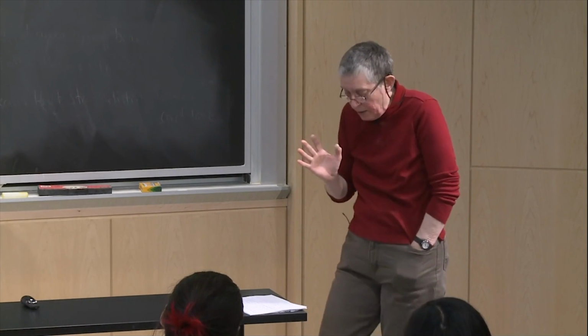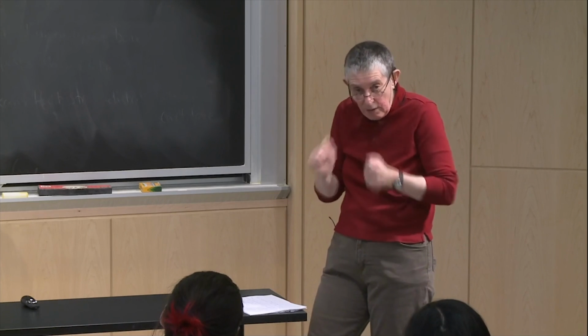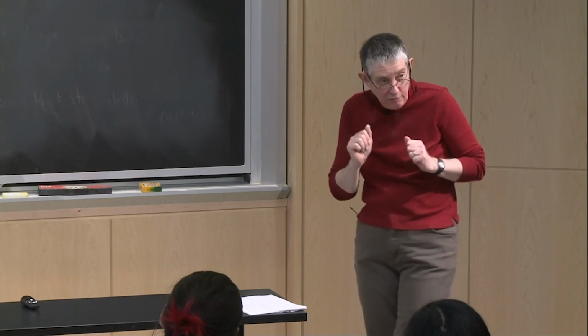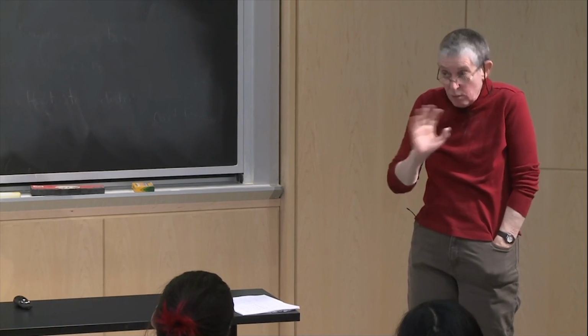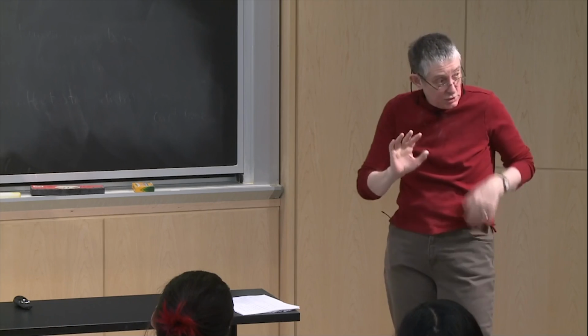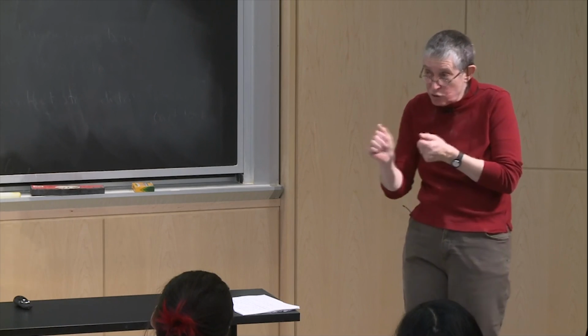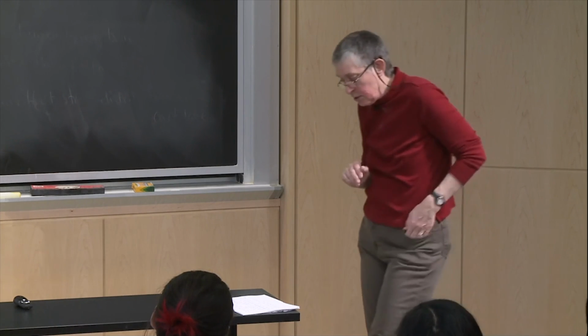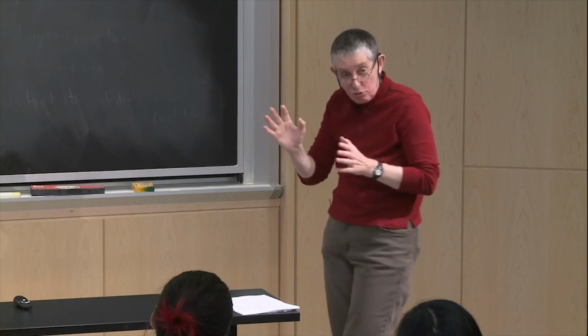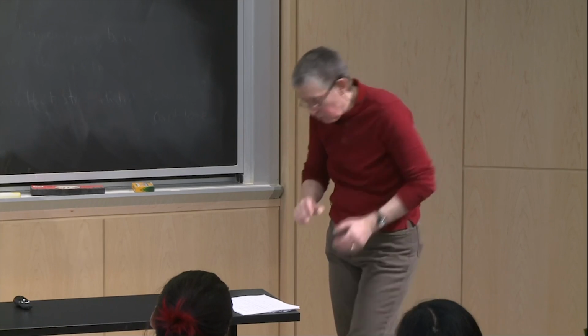And they find that the angle of the knee when the guinea fowl are running changes by about 14 degrees. And it turns out the orientation of the bone also changes by about 14 degrees. So the bone has remodeled to match that change in the forces that are applied as the guinea fowl are running on the treadmill. So this is all a demonstration to show that bone grows in response to load. So let me write down some of this stuff.